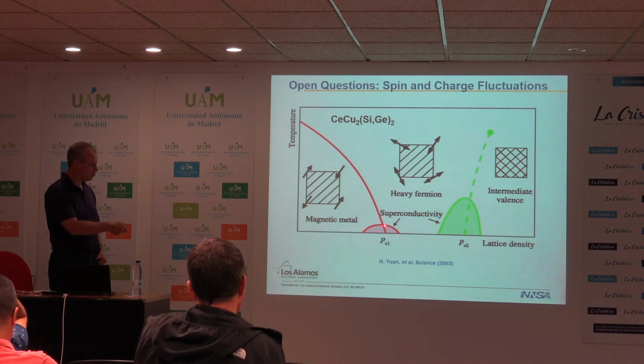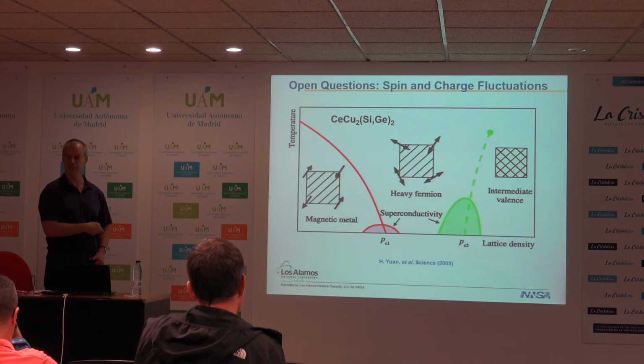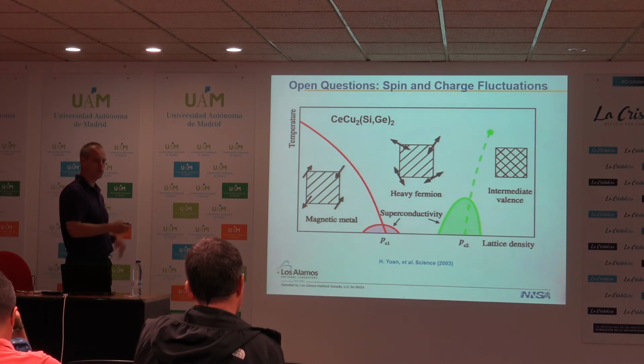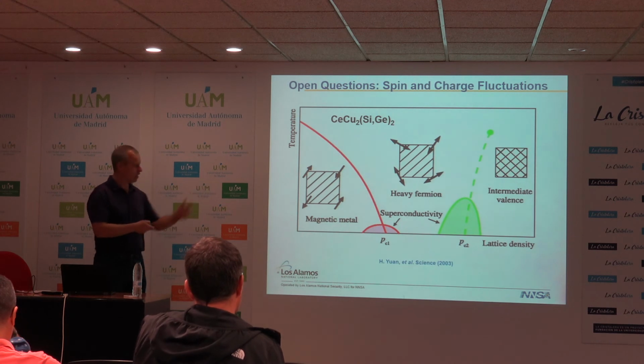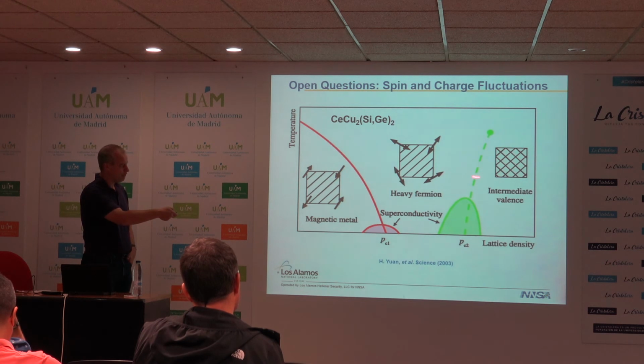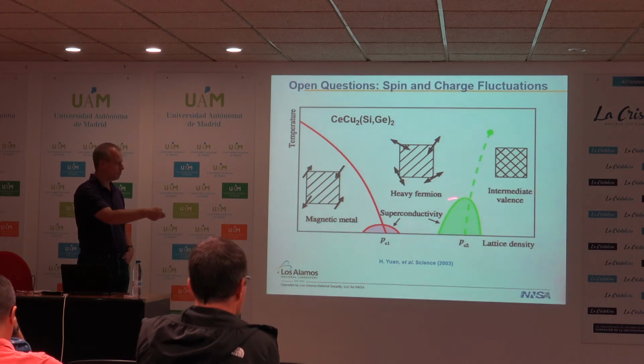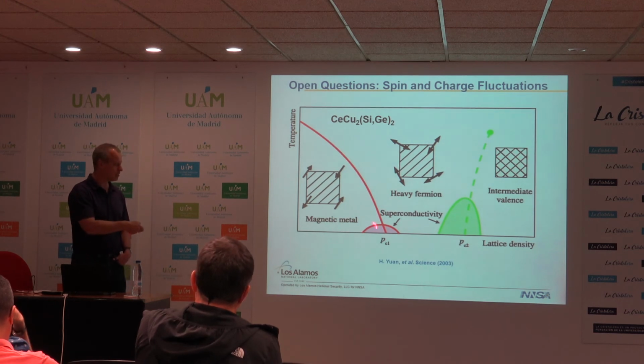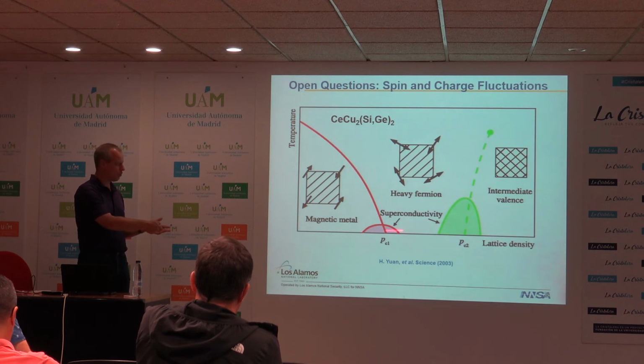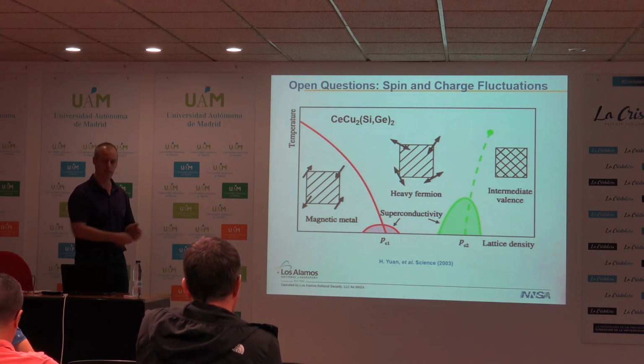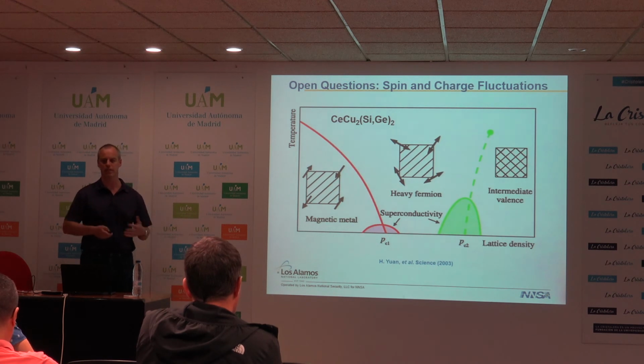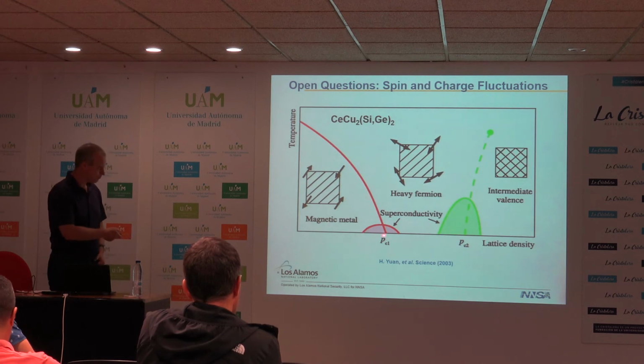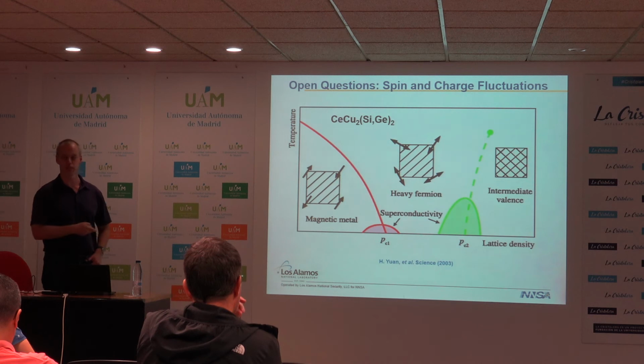What they found actually was they ended up with two distinct domes. They ended up with one dome which was centered right around this antiferromagnetic quantum critical point, and the second dome at much higher pressures, which actually seems to be associated with some sort of valence instability. So they believe, although it's not completely confirmed, that you have charge fluctuation sitting out here, and it's certainly clear that the TC around this charge fluctuating instability is much larger than the TC around the magnetic instability. The magnetic instability is one of a more conventional nature. So this large to small Fermi surface, even though it's not been measured here, the other properties of this magnetic quantum critical point seem consistent more with sort of what you expect for an itinerant antiferromagnetic SDW-like quantum critical point. So perhaps actually it is the role of the charge fluctuations that are more critical.